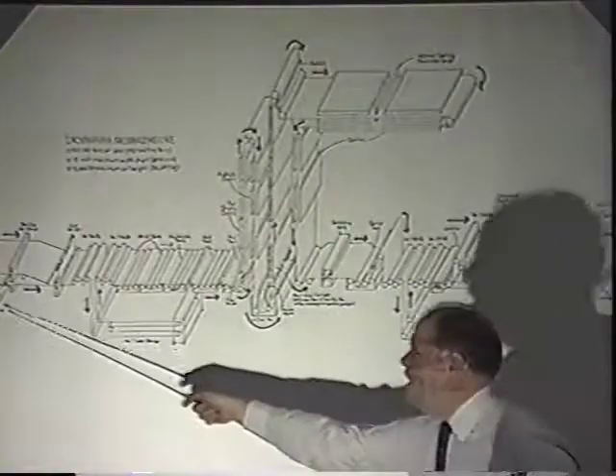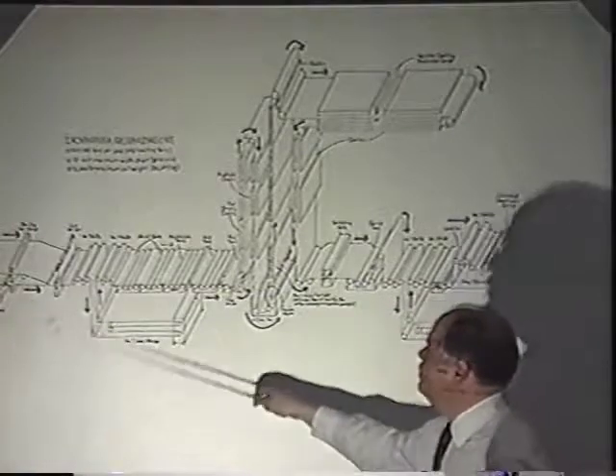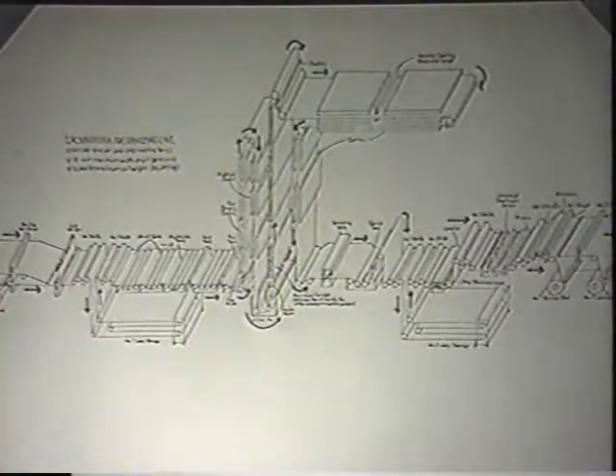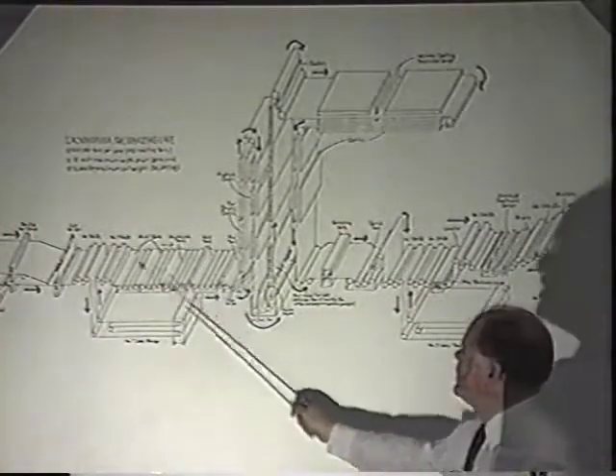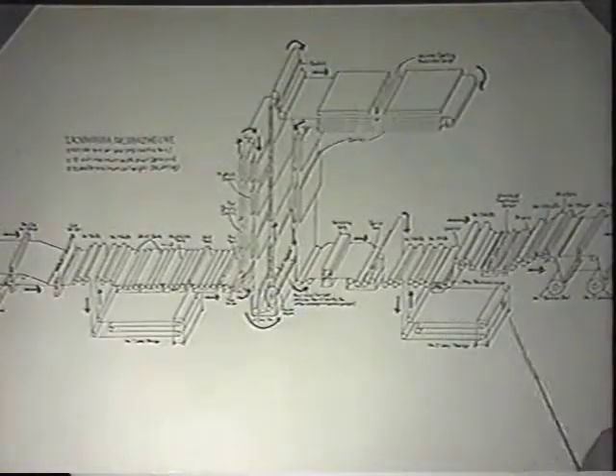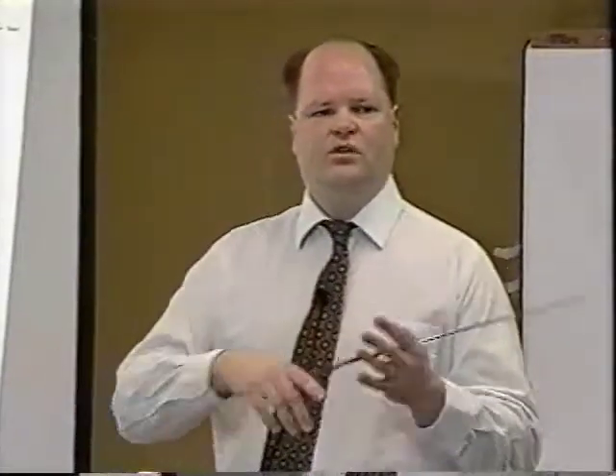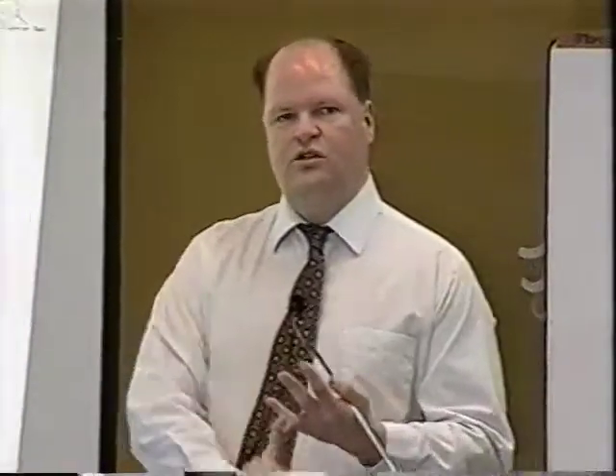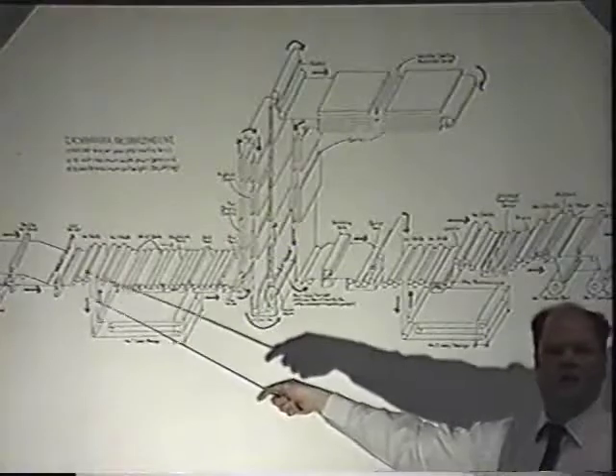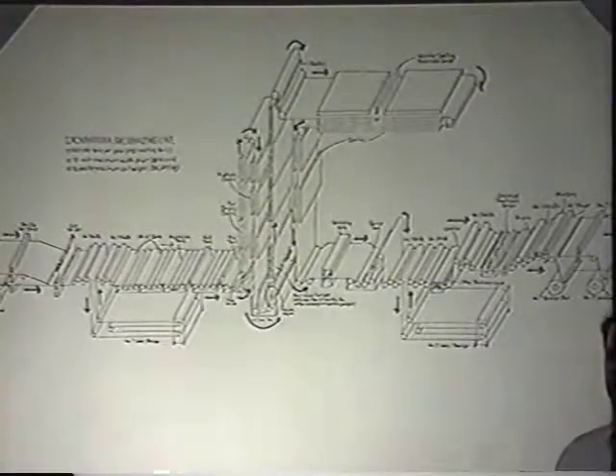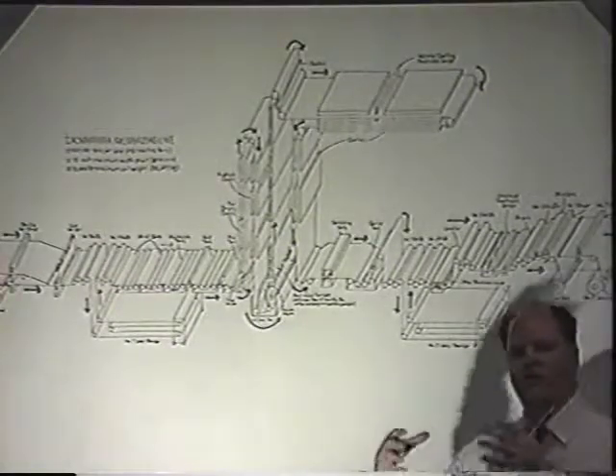It is a continuous line, so you still have the two coils here and a looping tower in the front and the back of the line. It still has a cleaning section. They still need a clean strip. And one thing they don't have is an anneal furnace. They don't anneal online like we do. So if they want all their coils, have to go from their tandem mill to their batch anneal to their temper mill before they can bring them to their hot dip line. So we have that efficiency of taking it right from the tandem mill to our hot dip line.